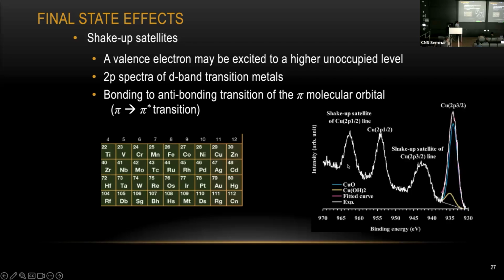For instance, the data shown here is a copper signal. This is the copper 2p3/2 main signal and 2p1/2 here. But you can see next to the main signal, we also see some satellite peak. Again, this satellite peak doesn't give you any chemical or physical information. It's just some additional peak you can pick up when you're working on any transition metal.